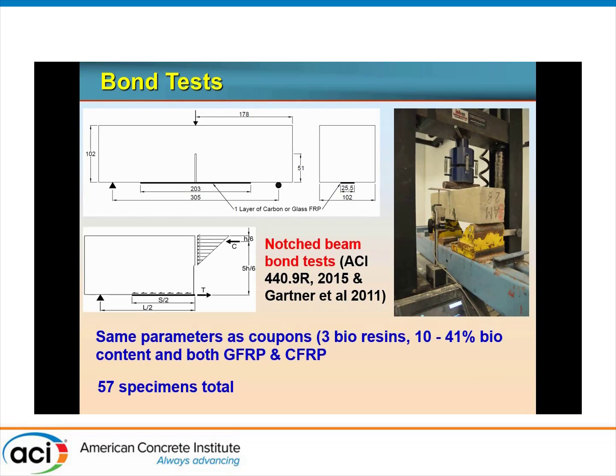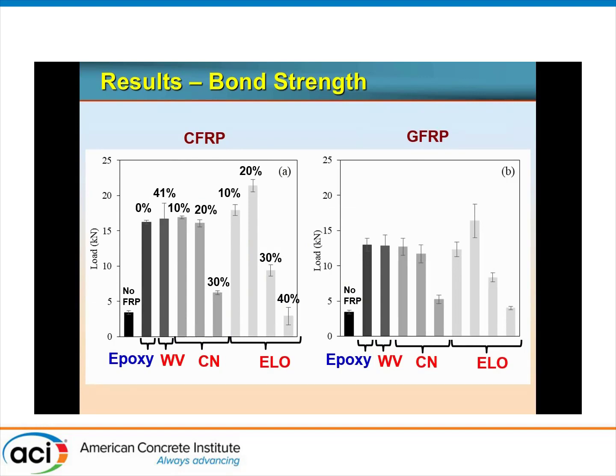We covered the exact same parameters as we did for the tension coupons. So the very first table, all 3 types of bioresins and carbon and glass, and we had a total of nearly 60 specimens. Direct to the results. Well, that's a notched beam that was not even bonded. There was no FRP at all here, but that doesn't matter. The epoxy is our reference, in this case for the carbon, which I call 0% bio, I guess. And then the WV system came fairly close. And then the CN 10%, 20%, and 30%.